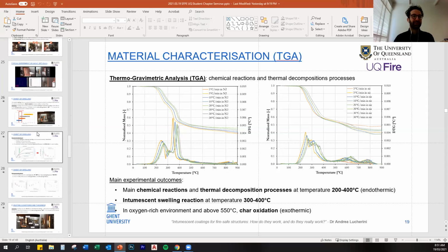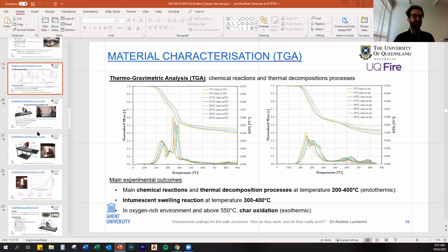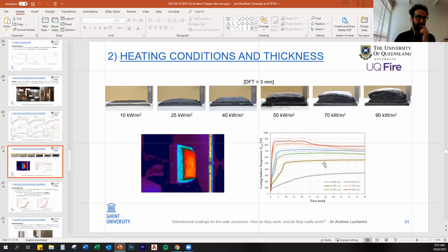So very good point. Thank you for the question. What I wanted to highlight to you is the temperature of the surface of the coating. The attendee is definitely right that in a fire we can expect higher temperatures than, for example, what I tested, up to 900 degrees, let's say. And we can expect 1,000, 1,100 degrees in a typical compartment fire.